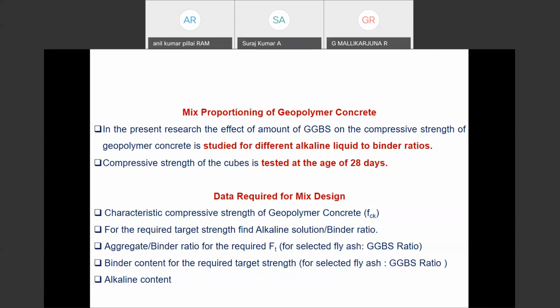After that, for formulation of this mix design, we considered different parameters. First, we decided we have to know the characteristic compressive strength of the concrete. After that, the alkaline to binder ratio. Next, we have taken the aggregate to binder ratio effect also. Whenever we increase the binder content, what is the effect of this particular amount of binder content in order to gain the strength?